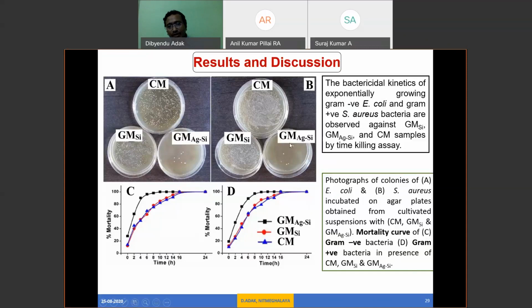Similarly, for gram negative bacteria we can see the same property. In the mortality curve, the black line denotes the silver silica nanocomposite based geopolymer mortar. After 2 hours, around 80% of bacteria are killed in the presence of the silver silica nanocomposite. But for the colloidal nanosilica based geopolymer and control mortar, bacteria are killed only up to maybe 60% or 55%. Then we have to wait a long time to study the mortality curve.